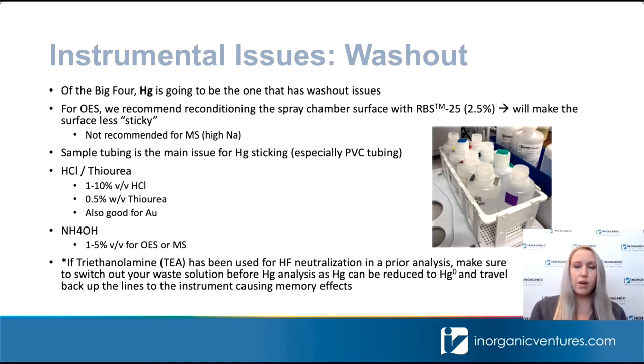But when you run mercury and it goes into a wash solution that contains triethanolamine, the TEA will reduce mercury to the metallic species. And since this is volatile, it can actually travel back up through the lines to your instrument and cause effects for mercury in the system. So just be aware of that. As I said, we learned that from experience.